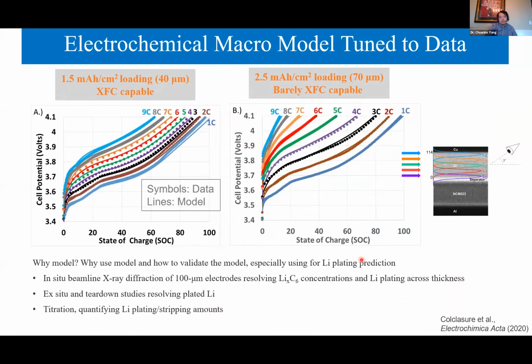In the Department of Energy's extreme fast charging program, a combination of cell testing, electrochemical and thermal modeling is used to investigate fast charging performance of cells with a low loading, 1.5 milliamp hour per centimeter square, and moderate loading, 2.5 milliamp hour per centimeter square. Cells with a low loading perform remarkably well, even up to 9C constant current, with very high Coulombic efficiency, charge acceptance, and very little plating observed. For a moderate loading cell, however, the charging capacity is poor. For example, at 6C constant current charge, a significant amount of plating was also observed.